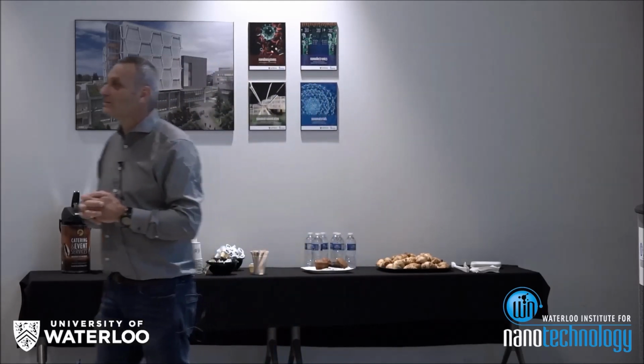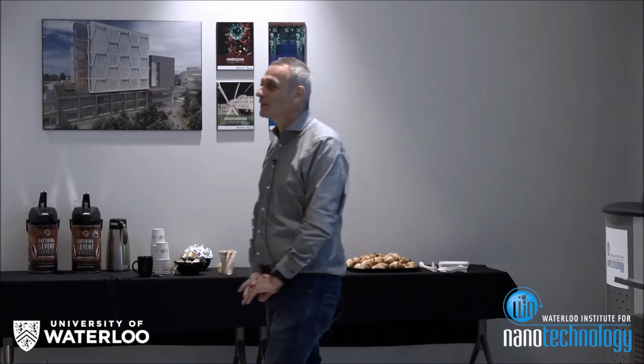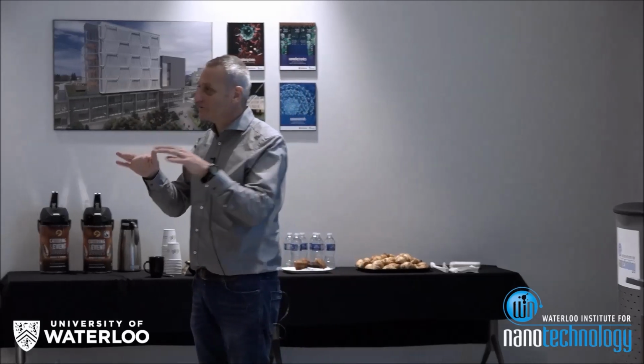I just had a second quick question too. Surface roughness is a problem with metallic nanowires, and I was just wondering if you looked into using ALD, zinc oxide, and aluminum oxide. Has that done anything to the surface roughness? No, because ALD is a very conformal coating, which is a good point, but then it doesn't reduce the roughness.